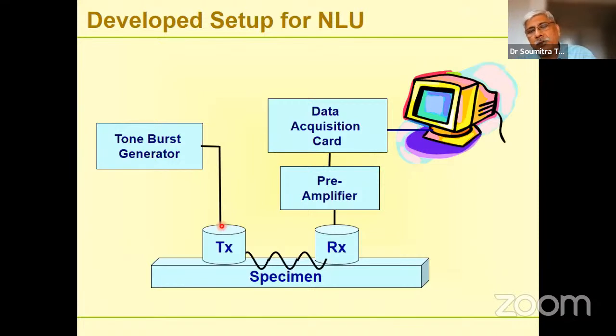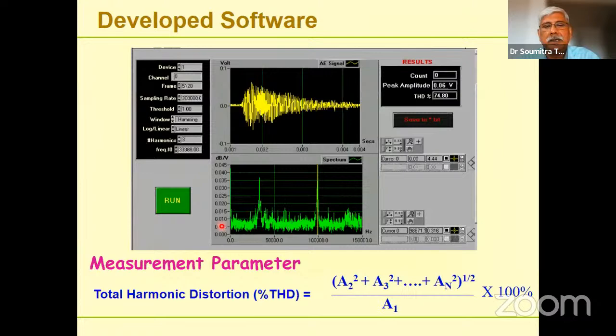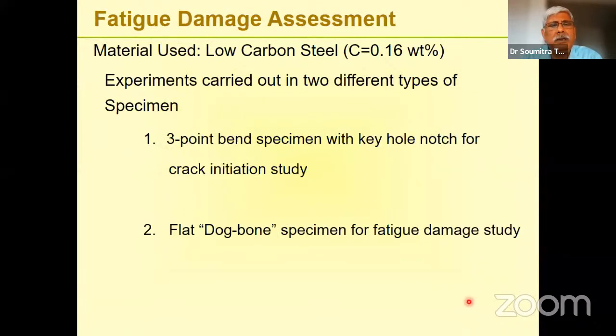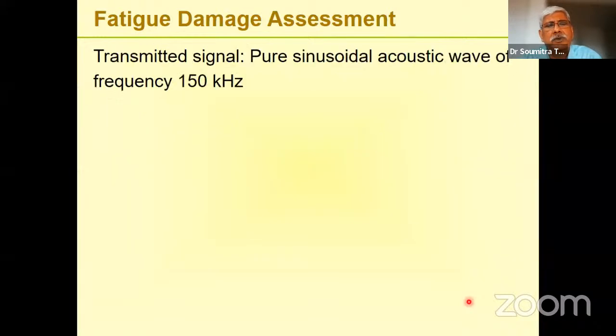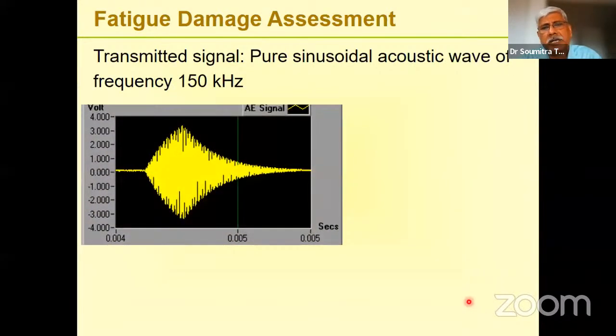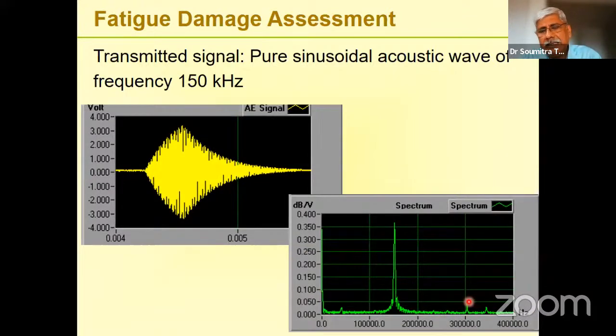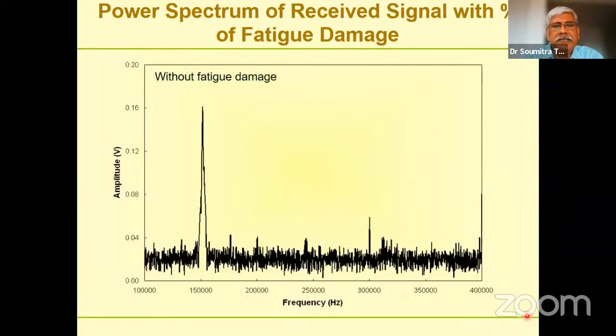So what we have done is we have taken a specimen, damaged it by fatigue, and then tried to monitor the nonlinear ultrasonic response of that specimen after it has been damaged, and looked at the total harmonic distortion that has happened in a square or the square root form. So again, this is what we have been doing, just zooming through that, using a pure sinusoidal acoustic wave of 150 kilohertz initially. And this is the output that you get, the primary signal and the harmonics if there are. And what we find is this.